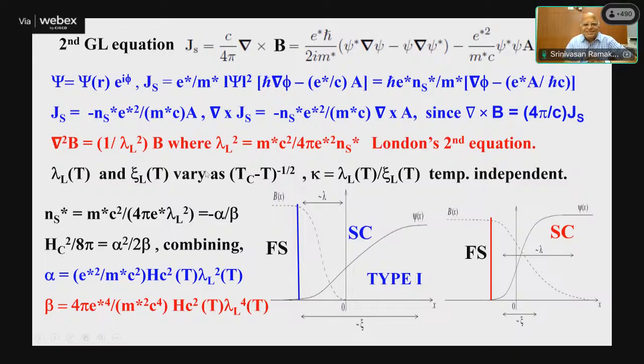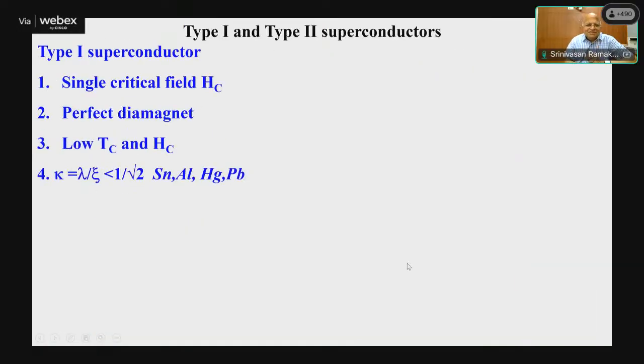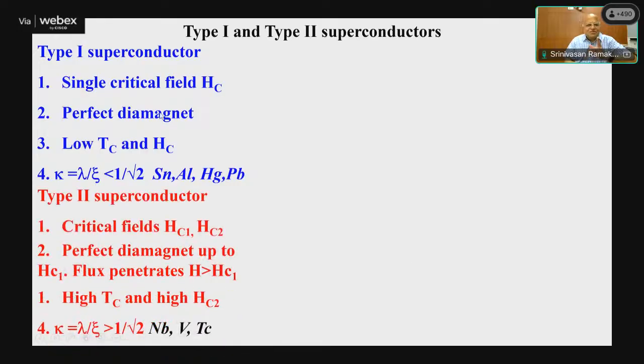So what he suggested was, from his theory, he was able to calculate the positive interface energy for type 1 and a negative interface energy for the type 2. How does this behave now? So for a type 1 superconductor, we have only a single critical field. It's a perfect diamagnet, low Tc and low critical field. So typical samples are lambda by xi less than 1 by root 2, where you have tin, aluminum, mercury, and lead, which are all type 1 superconductors.